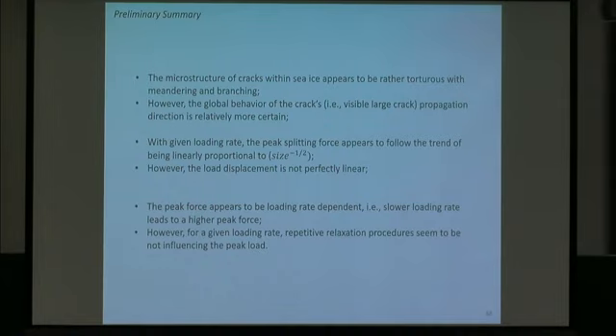such that we can capture it by our sensors. And regarding the size effect, it seems that given the loading rate, we did see that the test data is passing through this square root inverse size relationship. But it seems that load displacement is not perfectly linear, and they are somehow time dependent. And regarding the peak force, it appears to be loading rate dependent, judging from all these tests. But again, if we consider this cyclic loading, where we really wait until it heals or creeps or whatever, it seems that it's not influencing the peak load. So these summaries are just opening all these questions to me. What I plan to do is find a time-dependent material constitutive relationship and model to see if I can match my measurements. Okay, I think that's what I want to say. Thank you.